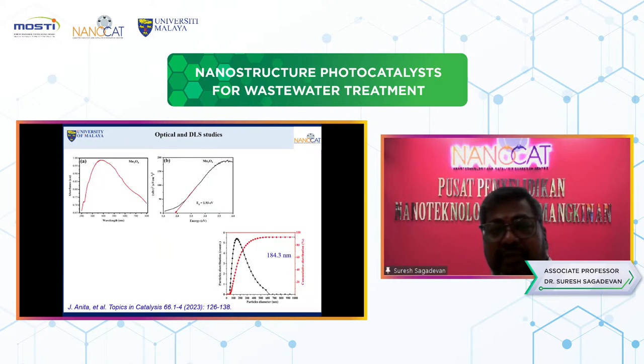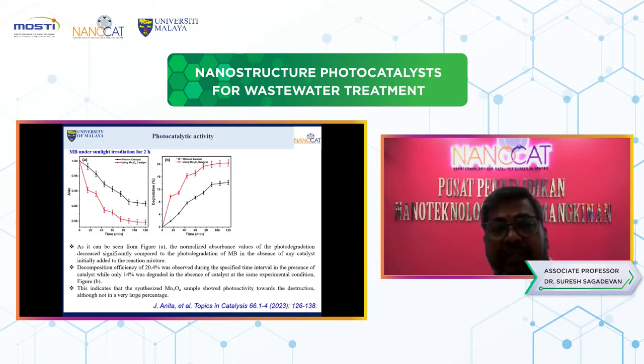Again, we did the UV absorption studies, where the maximum absorption occurred in the above 400 range, which means that the material has high catalytic activity and as well as the band gap value is very low. And as well as we did the particle size distribution. By using the DLS analysis, we found the particle diameter to be 184 nanometer. This we used for the photocatalytic activity using methylene blue dye under sunlight radiation for 2 hours. You look at here, there are without catalyst and with catalyst. You look at the absence of catalyst, as can be seen from the normal absorption value, no photo degradations.